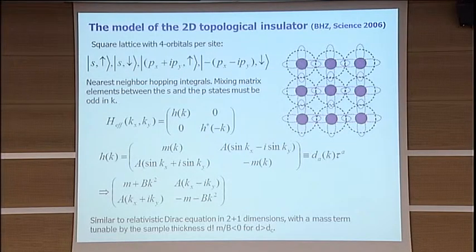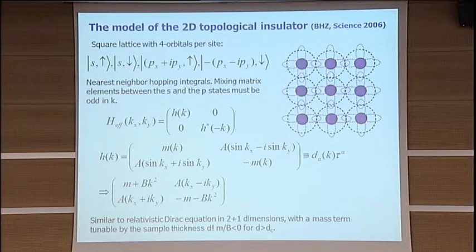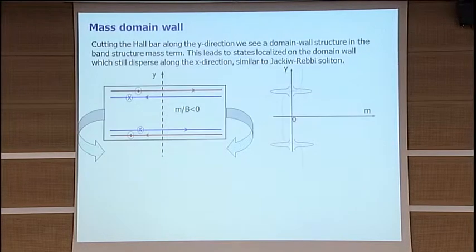You can not only change the magnitude of the gap, you can also change the sign of the gap — because mercury telluride has a negative energy bandgap and cadmium telluride has a positive energy gap. As you tune the relative thickness of mercury versus cadmium, you can tune the level difference between S and P, inducing a topological phase transition. This was pointed out by my former students Andrej Bernevig, Taylor Hughes, and myself in a Science paper in 2006.